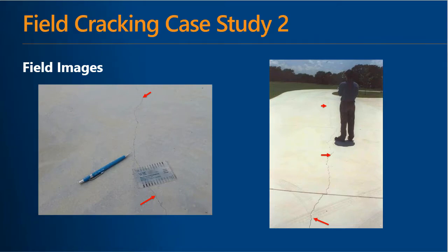These types of cracks are caused by restraint, whether that's internal or external. Typically, it's an external restraint, but there can be internal causes as well. And they may occur as full width pavement or slab cracks, like the cracks shown on the left, or transverse cracks in bridge decks or parking garages. In the right-hand image, you can see one of our petrographers standing on a concrete driveway that was somewhat recently placed. You can see that there are some saw-cut joints, roughly horizontal in the image, but then you can see that there is a nice crack running down the middle of each of these panels.